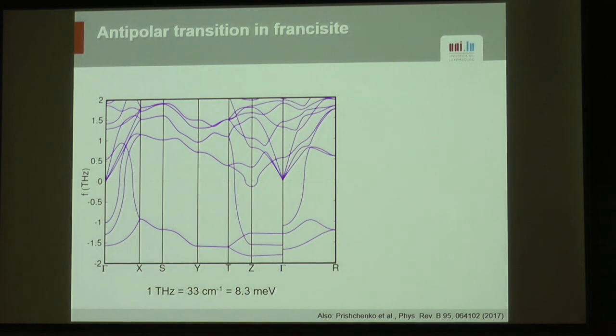Next thing we want to look at is the phonon band, so very much also in the spirit of what Jorge has been discussing. So this is what it looks like for the high symmetry structure. You have actually a bunch of unstable modes, but essentially the feature that you're looking for is here. So you will find the most unstable mode is the Z one, so the antiferroelectric one. And you have also an unstable mode at gamma that is just slightly less unstable. So that looks very good.